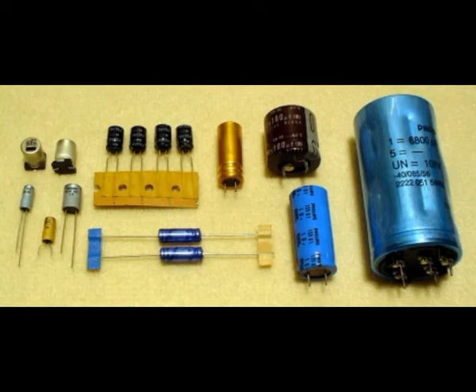The FIT values given in data sheets are calculated from the long-time experience of the manufacturer, based on the lifetime test results. Typical reference failure rate values for aluminum electrolytic capacitors with non-solid electrolytes are, for low voltage types 6.3 to 160 volts, FIT rates in the range of 1 to 20 FIT, and for high voltage types greater than 160 to 550 volts, FIT rates in the range of 20 to 200 FIT.